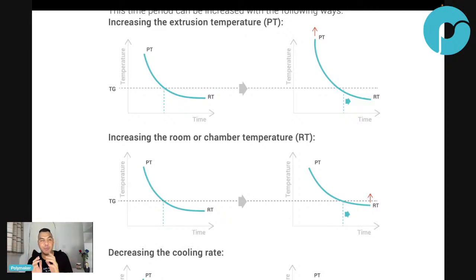So that's why we go to semi-crystalline. That's why we solve that problem with semi-crystalline. That's why you can print polyamide copolymer or whatever other nylon very easily, no warping issue, and it has a very high temperature resistance because we use crystallization instead of this. So it has a low TG, easy to print. There is another thing. By the way, guys, we only touched one part of warping. This is for amorphous material, this is for the amorphous region. The semi-crystalline is completely different. I mean, the amorphous region will have the same problem, but they have an extra problem, which is crystallization. And that's how our warp-free technology works, because we manage the crystallization rate of the semi-crystalline.